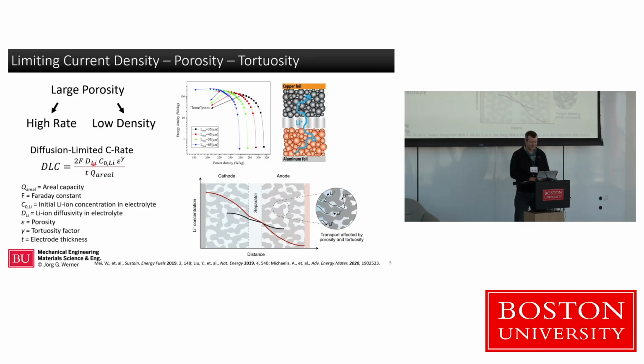There's the thickness of your battery here, right? That's what we have seen here. The thicker your battery, the slower you have to charge it. And then there is the porosity here. That makes sense. We mentioned that before. But there's also this gamma factor here as an exponent. That's what's called the tortuosity factor. That's essentially describing how tortuous is the path to get from one side to the other.